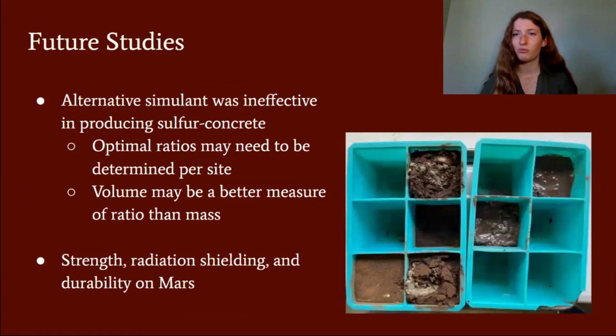So something else that was really interesting that happened, I accidentally used a different simulant. It was slightly different. It was sent from previous NASA contact and it didn't work. You can see here, it did not cook sulfur concrete. This is the one I ended up actually using and had used in the past. So that suggests that optimal ratios, finding that is a lot more complicated and it might need to be determined per site. And also volume might be a better standardized measure of the optimal ratio than mass, which is what all the previous studies have looked at. However, volume is actually used a lot when making actual concrete on Earth.